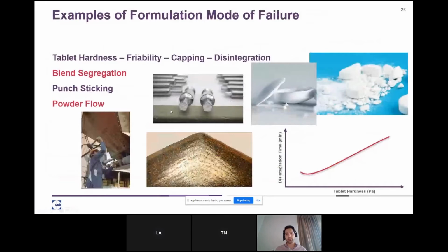So now I'm just going to talk about some examples of formulation modes of failure. Of course, as the powder goes through the process, we face failures, and we need to investigate the root cause. Here are some examples. First, tablet hardness, how hard the tablets are, could be linked to friability, whether the tablets break or not. After tableting we have the coating, with a tumbling bed where the tablets are tumbled in a drum and then you apply the coating agent. During this process the tablets can actually break.